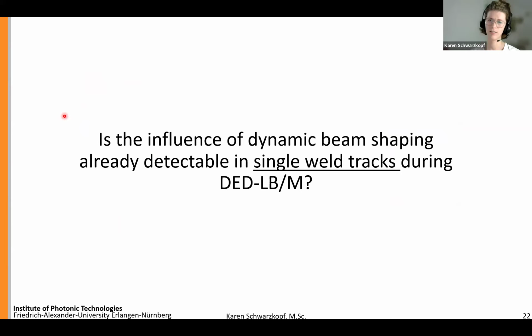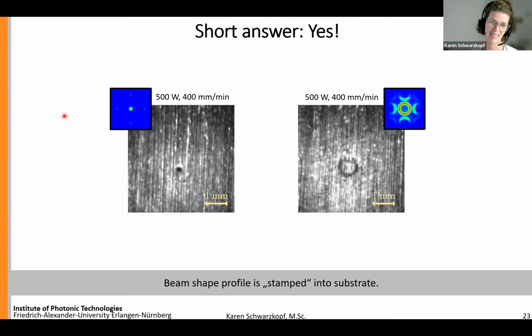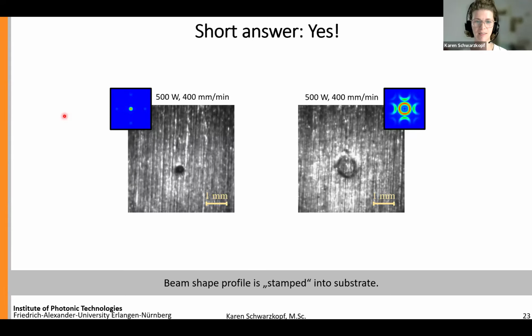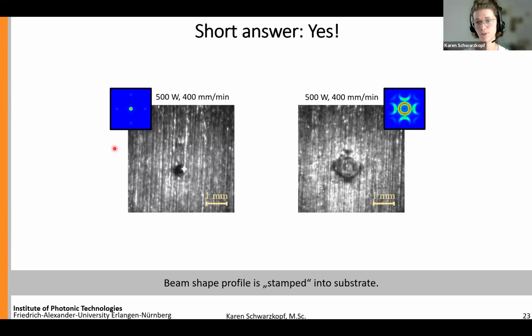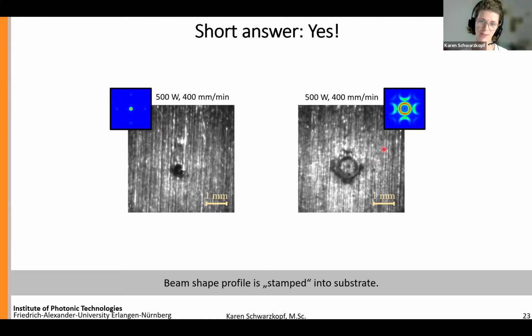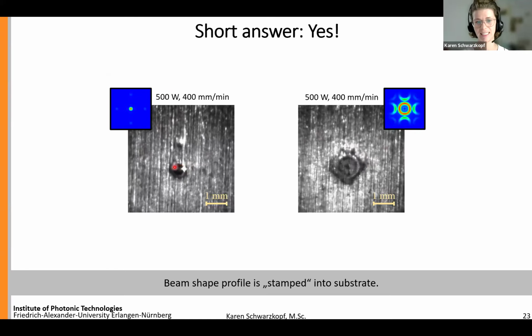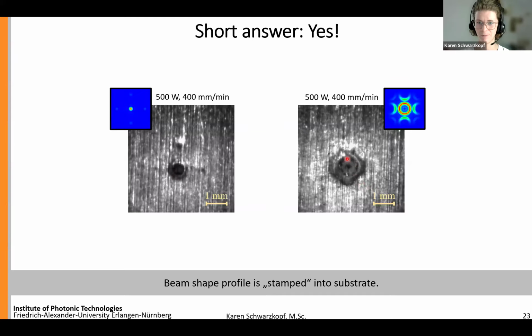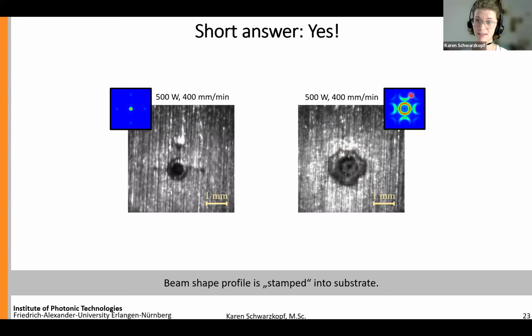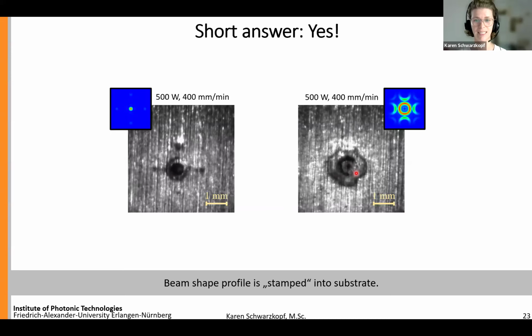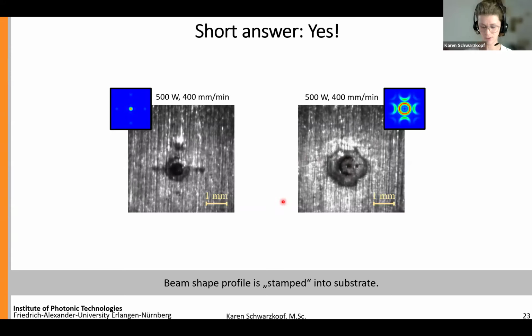Now, the first question that we were asking ourselves is whether the influence of dynamic beam shaping is already detectable in single weld tracks during the DED process. And for those of you who know my presentation already, the short answer is yes. This is visualized here in these 2 high-speed videos that compare the point intensity distribution to a ring distribution. As you can see, it's not only the size that is differing for the 2 beam shapes, but also, for instance, the influence of these higher modes, and the powder impingement is happening earlier for the ring. So basically what follows from this video is that the beam shape is stamped into the substrate.